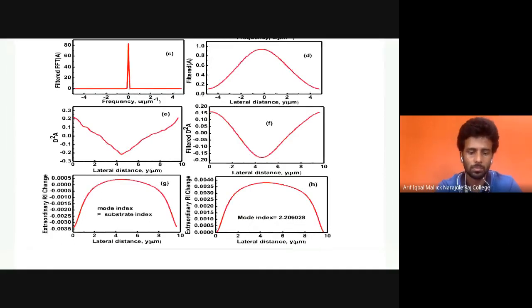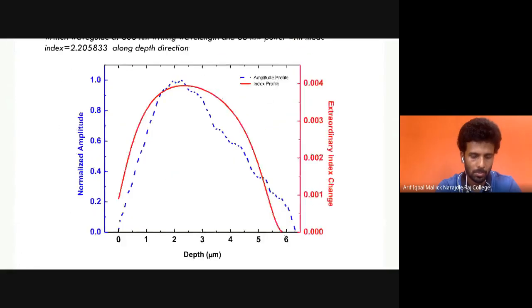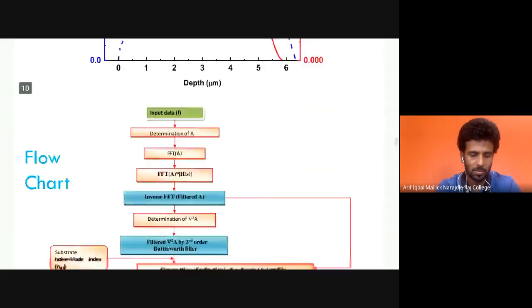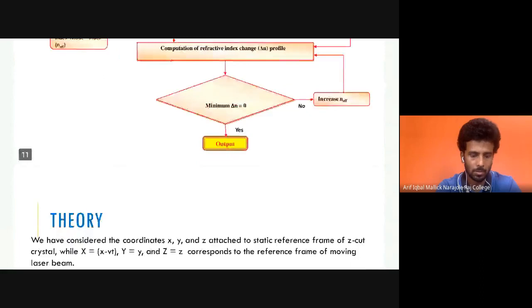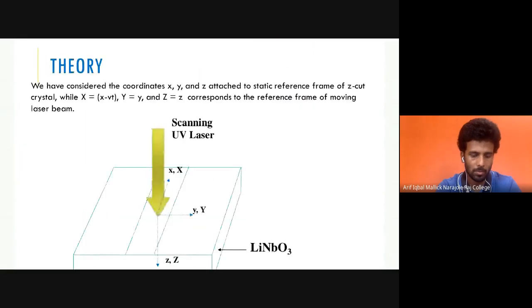So we gradually increased the mode index from the substrate index, until the minimum refractive index change is 0, and obtained the actual refractive index profile, given in figure 8, with mode index 2.206028. It is the same refractive index profile from the amplitude profile along the depth direction, with mode index 2.205833 along the depth direction. This is the flow chart of my computation. Finally, the theoretical approach.